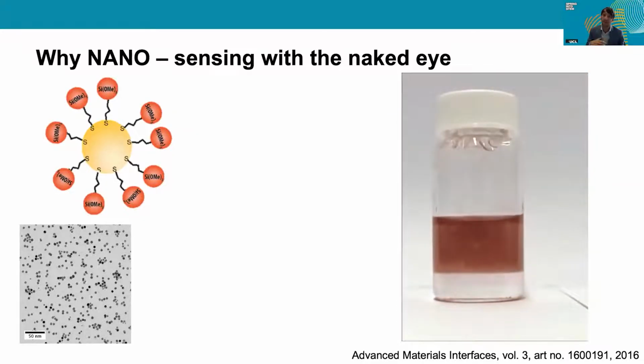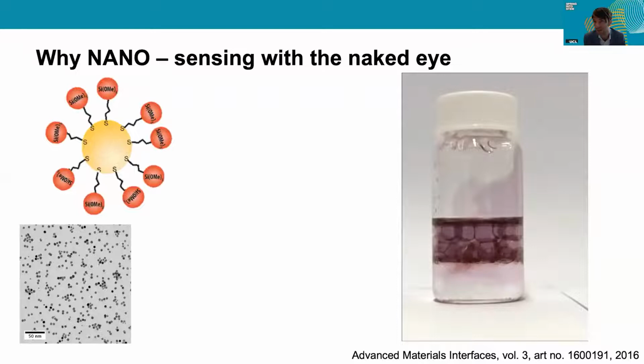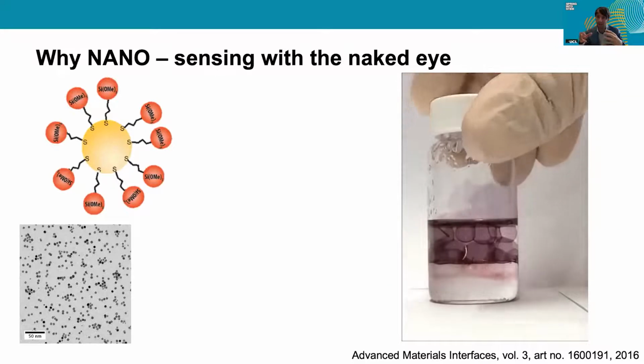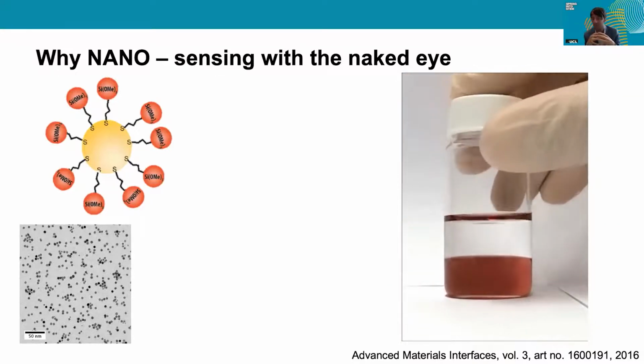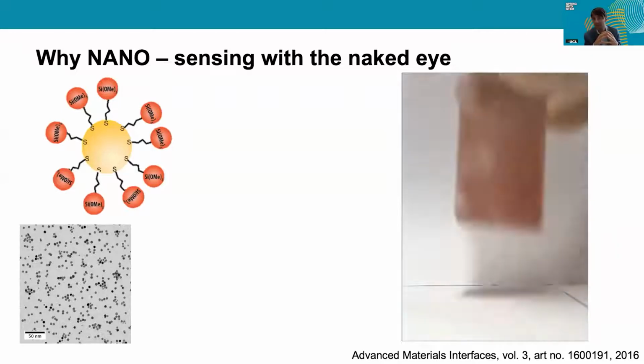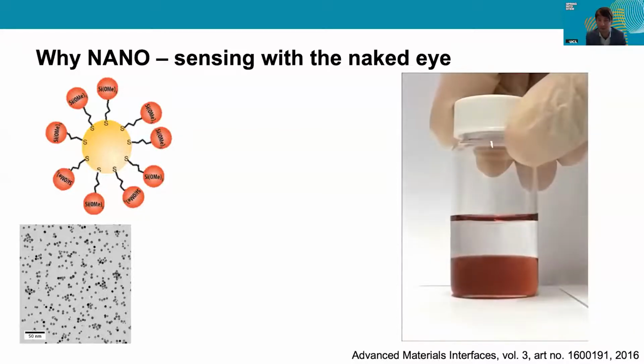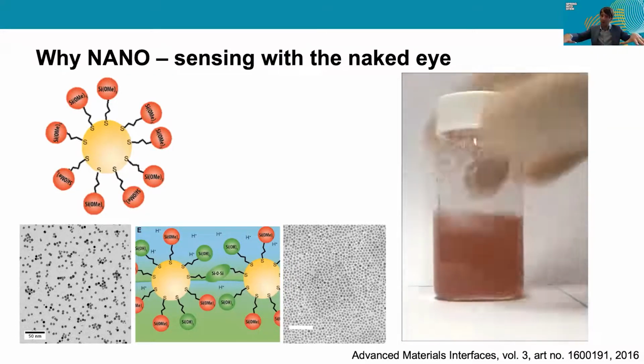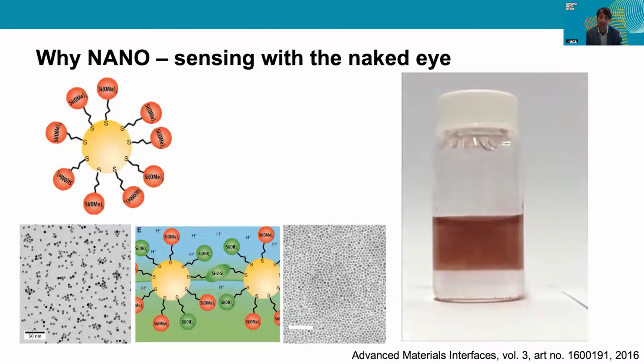what's happening is that the particles get to the water interface and they are getting hydrolyzed. And then when they're hydrolyzed, they become reactive. And when they see another particle, they start to stick together, just like Velcro. And therefore, you've kind of forced them to form a membrane, to form a layer by hydrolyzing them, by making them reactive. And this process can be used, and it's showcased here, to make a very thin layer of gold nanoparticles.